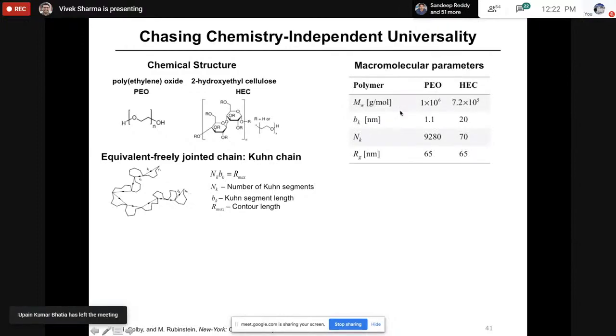She picked molecular weights that are comparable, but the Kuhn segment of HEC polysaccharide is much longer, 20 times this. The number of Kuhn segments is much larger in PEO, which is also the case because this is small, so this has to be large. And this shows that this is fairly flexible and will be more extensible than HEC. But if you calculate the coil size, it comes out to be the same.